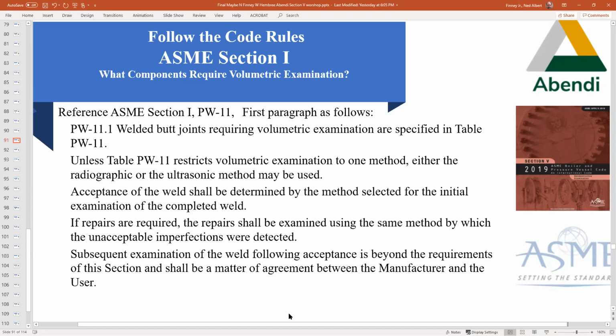Acceptance of the weld shall be determined by the method selected for the initial examination of the completed weld. So in other words, you do radiography on it, you don't like results, you can't go back and do ultrasonics on it. And you use the acceptance criteria of that method that was used. If repairs are required, the repairs shall be examined using the same method by which the unacceptable imperfections were detected. Again, if radiography was used to deem that welding flaw unacceptable, therefore rejectable, and a repair was made, then you come back and use the same method, radiography. Subsequent examinations of the weld following acceptance is beyond the requirements of this section and shall be a matter of agreement between the manufacturer and the user.